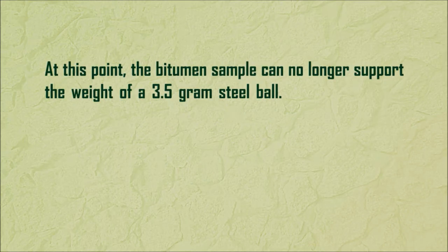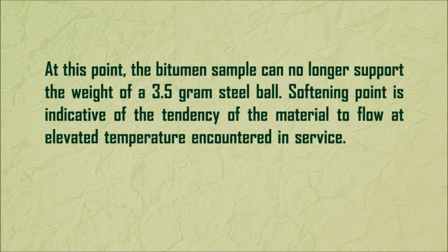At this point, the bitumen sample can no longer support the weight of a 3.5g steel ball. Softening point is indicative of the tendency of the material to flow at elevated temperature encountered in service.